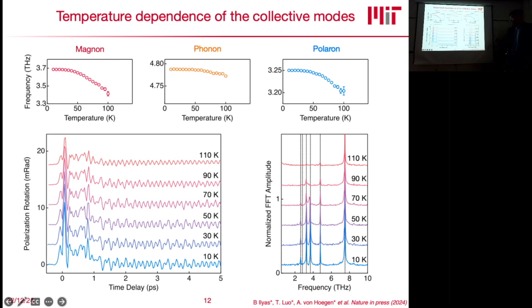And so then we went again one step further, and asked how this coupling evolves as a function of temperature? And this is something you can see here. So the magnon starts softening, the phonon is basically constant, and this magnon-phonon mode also starts softening. This increased softening of the magnon-phonon indicates an increasingly strong coupling close to the transition temperature, which is around here at 118 Kelvin.